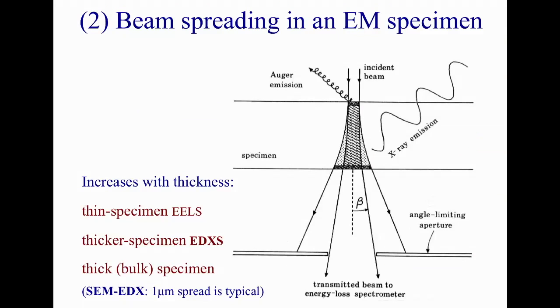Despite all these precautions, there are some physical effects that can limit our object resolution, and one of these is called beam spreading or beam broadening. Our analytical signals are generated by inelastic scattering of the beam electrons, which involves very small scattering angles. But the structural information in TEM images comes mainly from elastic scattering, which involves deflection angles that are large enough to cause a focused beam to spread laterally as it moves through the specimen. This is a minor problem for EELS, where the specimen is very thin, but it can be appreciable for EDX spectroscopy. It becomes a major limitation in an SEM, which uses a bulk specimen, and where beam spreading limits the spatial resolution of X-ray maps to some fraction of a micrometer.